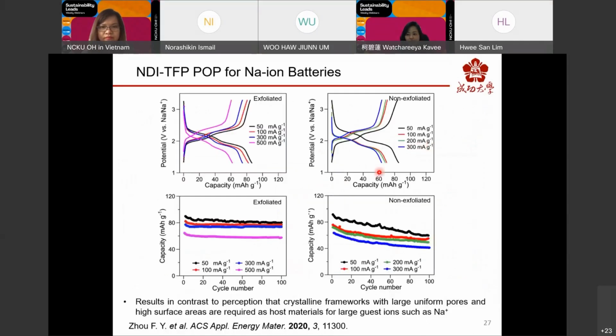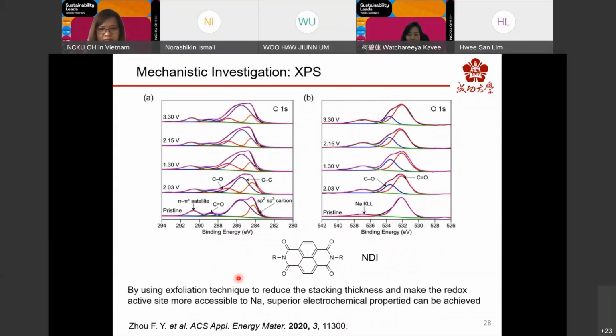And these results are in contrast to the perception that crystalline frameworks with large uniform pores and high surface area are needed as host materials for large guest ions, such as sodium ions. Now, by using an exfoliation technique to reduce the stacking thickness and also to make the redox active sites more accessible to sodium, superior properties can be achieved.